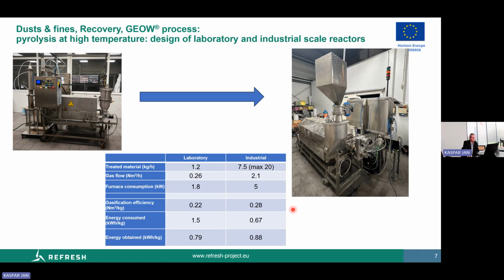But the important thing, I think, is that we obtain a significantly higher amount of energy from the gases that are produced in the product. We don't consider the energy content of the char, which comes out of the reactor together with the gas, and which can then be treated under oxidative conditions to generate further heat, which is quite high. But these values, to be honest, are quite low in this case, because we have been using materials which have a relatively low carbon content. When we start from some other materials, we can obtain an energy which is about even twice that employed for our treatment.